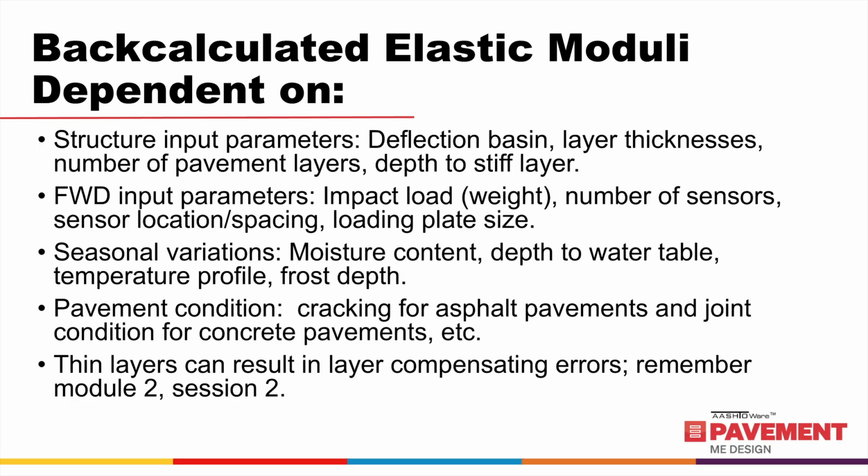The back-calculated elastic layer modulus values are representative of the conditions at the time of deflection testing. After that, pavement condition like cracking for asphalt pavements and joint condition for concrete pavements can also affect the field modulus. Neither cracks, joints, nor other defects can be directly simulated in EverCalc, and as such the BCT back calculation program. Finally, thin layers are difficult to analyze in the BCT and other back calculation programs that are based on elastic layer theory. Remember, thin layer was defined in a previous Module 2, Session 2 under the rules of layer simulation.